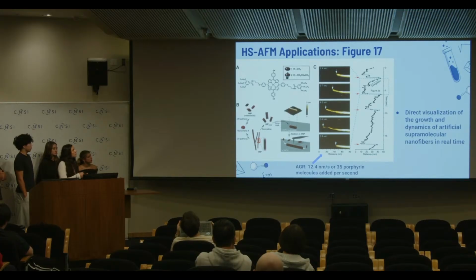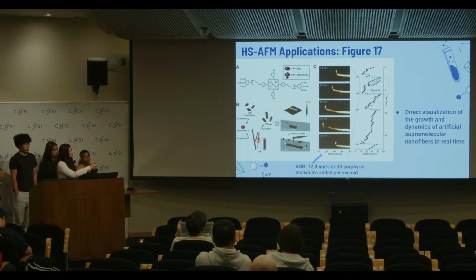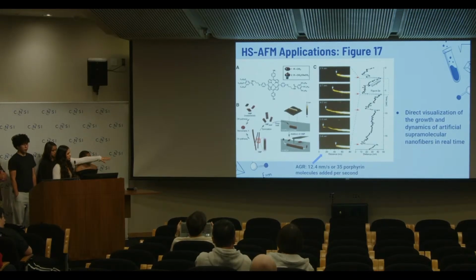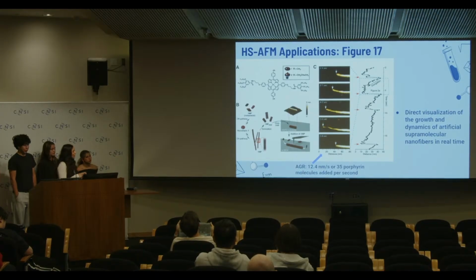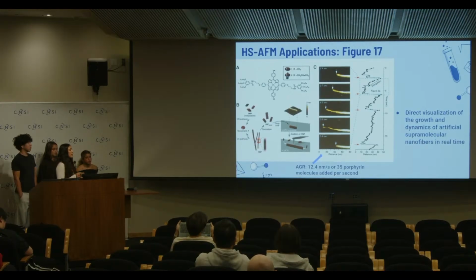What high-speed AFM allowed scientists to do was take images every 0.1 second, so they were able to watch this whole process in real time. As you can see, there's 2.4 seconds, 2.7 seconds. And if you look at the last image at 5.8 seconds, you see that the nanofiber suddenly is about half the size of the image before. This is due to breakage of the nanofiber, but it's most likely due to the nanofiber coming in contact with the probe and the force that results from that. What scientists found was that the average growth rate was 12.4 nanometers per second, or 35 porphyrin molecules added per second.